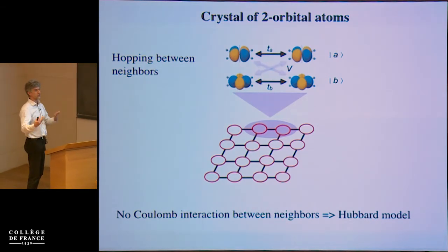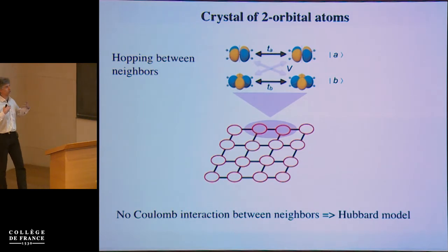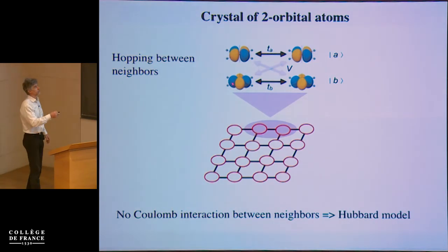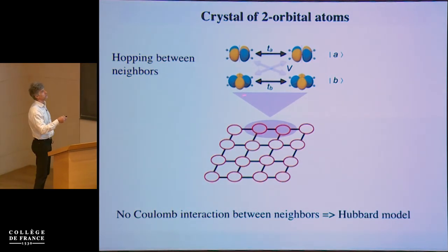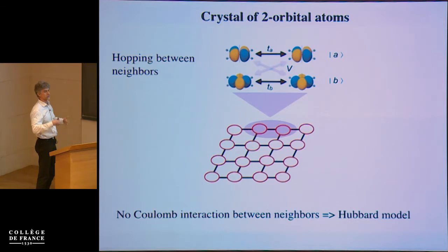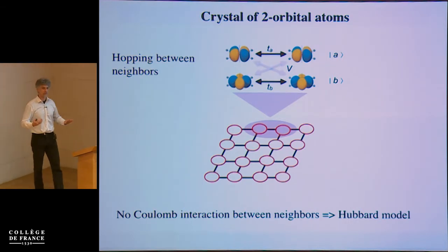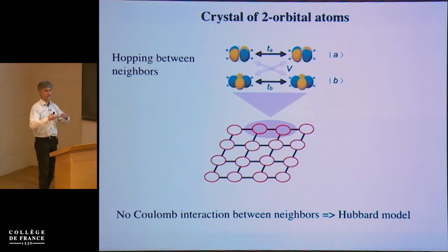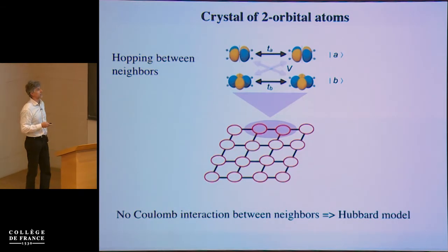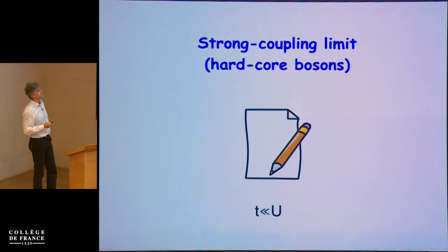This would typically be a perovskite structure where you have hopping only between T2G and T2G, and EG to EG. And we will consider some small hopping between different orbitals. In a real material with perovskite structure, you can imagine some tilting of the octahedra, which would give rise to this kind of hopping.